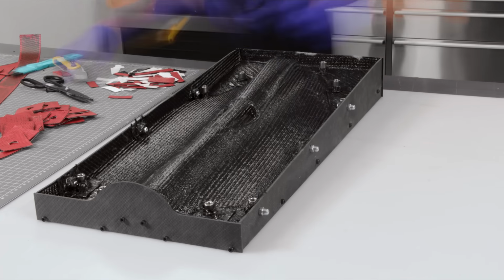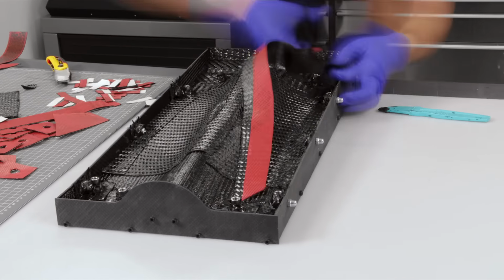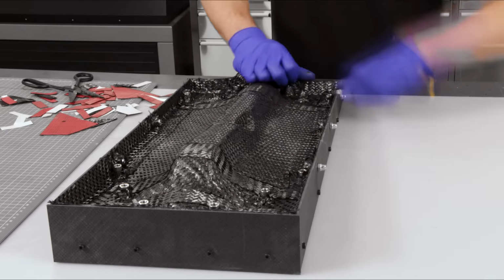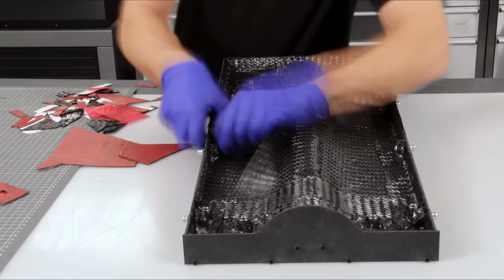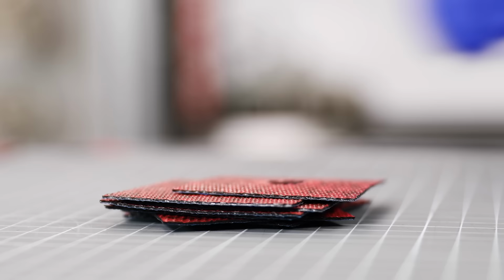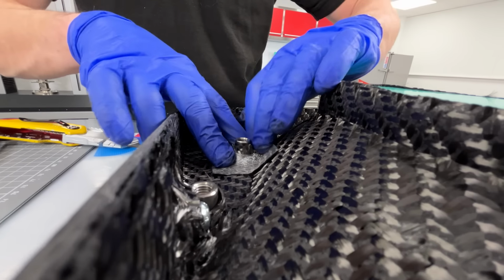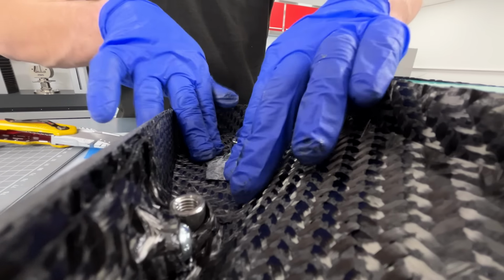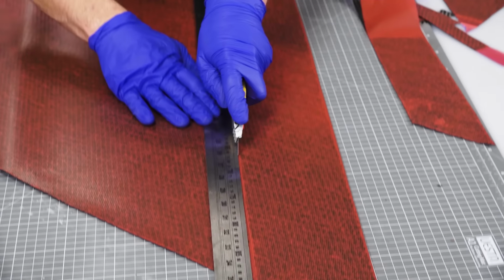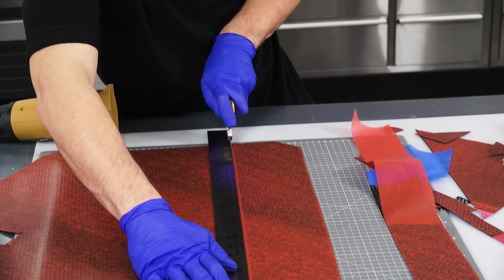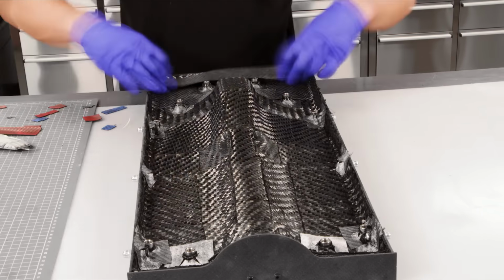For optimal mould stability, it's also best practice to flip the backing ply upside down at the mid-plane and continue to laminate with the resin-rich side facing up. I've chosen not to do that here as it makes the laminating more time-consuming, and being such a small and contoured mould, it would have negligible effect on the accuracy. But for larger and flatter moulds, I would normally follow best practice here.